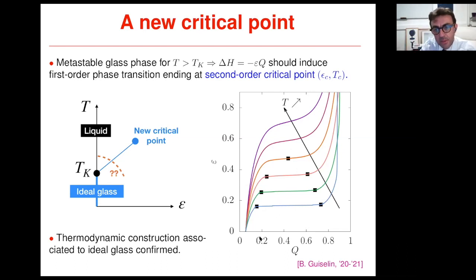So here what we do is we follow the increase of the overlap as a function of this field epsilon. So we have a smooth increase of the overlap at high temperature because we go above this critical point here. And when we cross this blue line here, we have a discontinuous jump of the overlap across this first order transition blue line. So these results show that the entire thermodynamic construction associated to the existence of an ideal glass phase can be rather convincingly observed in three-dimensional systems.